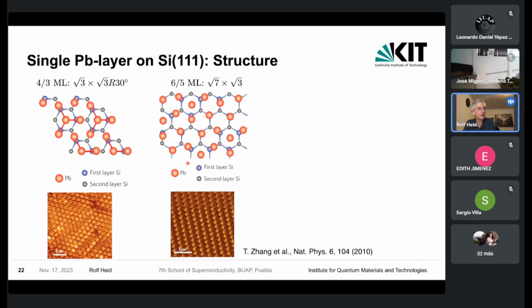Now, what is happening, of course, in this case is that you really get a specific kind of structure of this single atomic layer, which is really tightly bound to the surface. Shown here is one of the phases which have been observed, the so-called 4/3 monolayer lead film on a silicon 111 surface. So you see the silicon atoms below, and then the lead atoms sitting on top. 3 of the 4 atoms are sitting close to a silicon, and they make essentially a covalent bond to the silicon on top of the surface. And then the 4th lead is sitting in between in this hollow site, and builds essentially some kind of metallic bonds to the neighboring lead atoms.